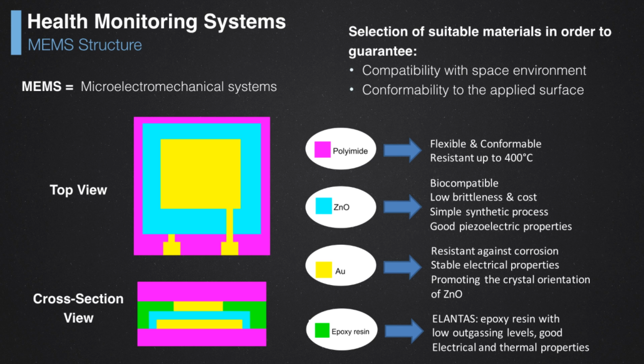What about the typical structure of the device that we have realized? So I told you that in the case of the fuel tank, we have cylinders to be coated, and we wanted to have a fully flexible, conformable device. So we selected polyimide as a substrate. Polyimide, which is also known as Kapton, the commercial name of this compound, is one of the most performing polymers ever invented because it's able to withstand temperatures as high as 400 degrees without melting. Its mechanical strength is huge, comparable to certain metals. Of course, it's a polymer, but the Young modulus is extremely high. We used this as a substrate.